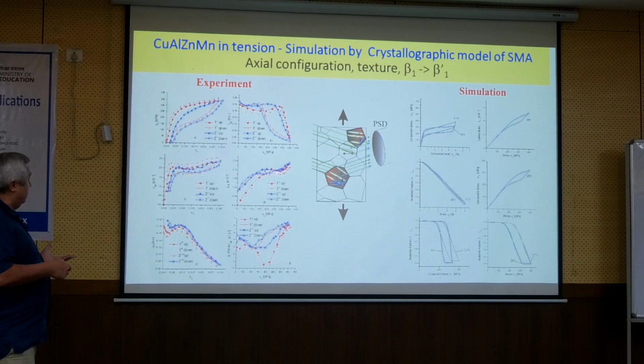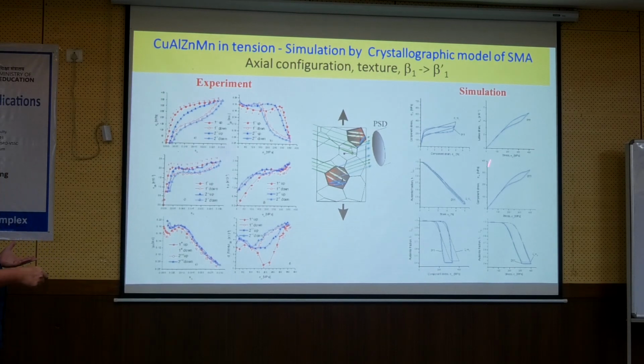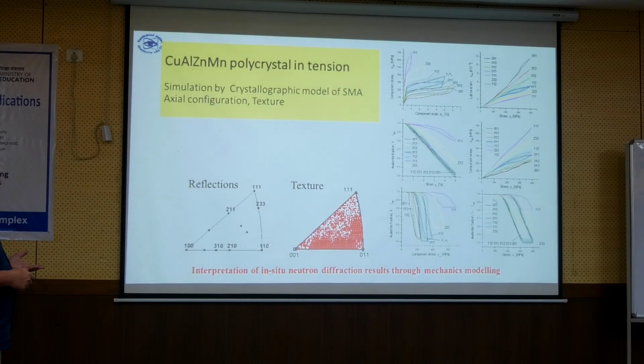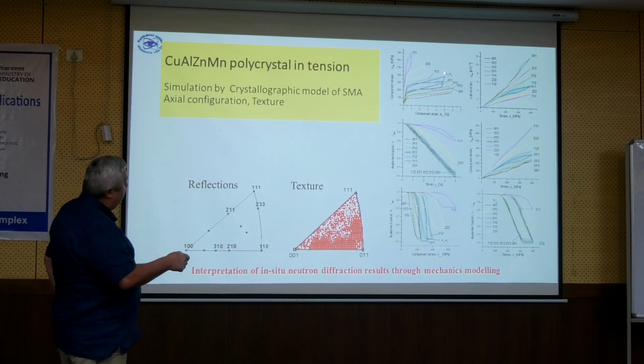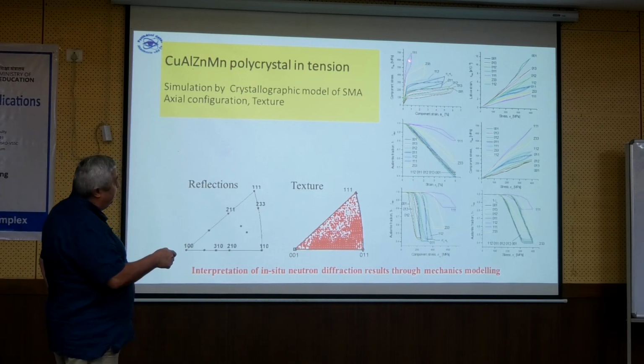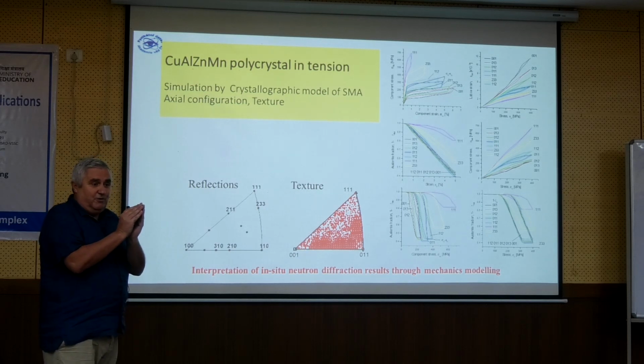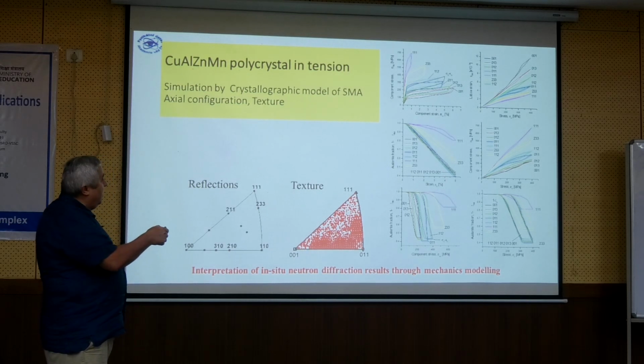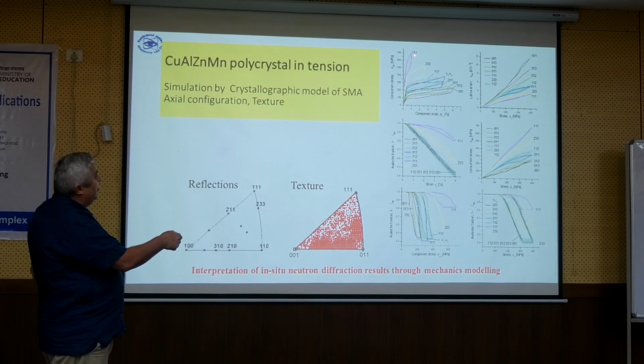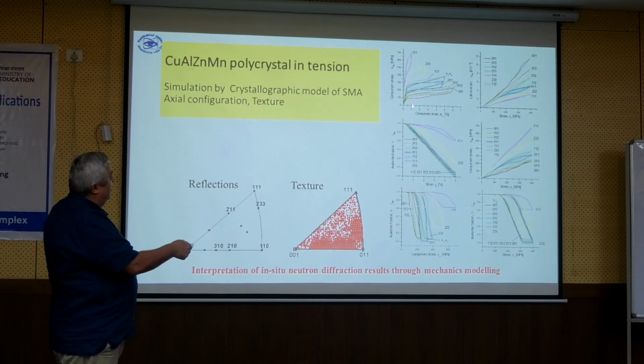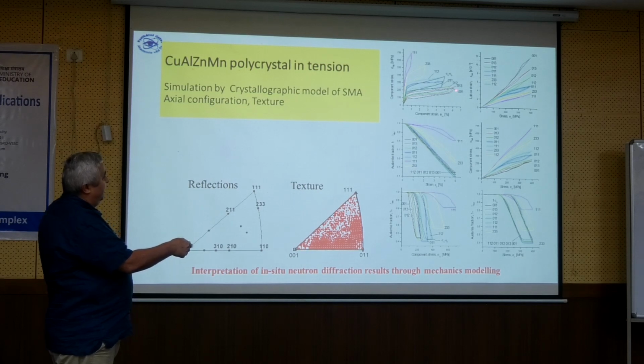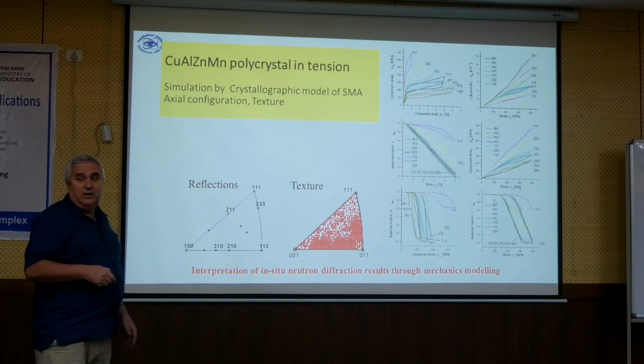We find out that many of the experimental responses which could be observed in this diffraction experiment actually can be reproduced. So if you look on this diagram, here the black is the macroscopic curve, and this is the behavior of differently oriented families of oriented domains. In this domain, you can impose only very small strains, and you have very high stresses. In this grain, you have very large strain, but the stresses are very low.